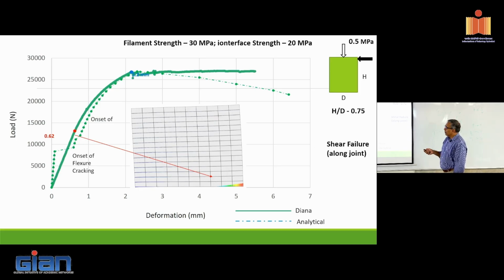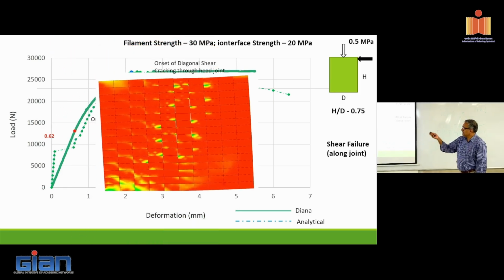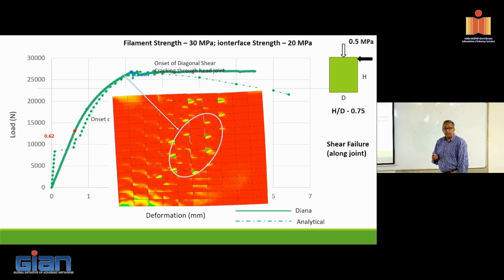Now I can do a micro model. Micro models are available where the constitutive models of these horizontal and vertical lines represent the mortar interfaces. And I can get the constitutive properties from the shear tests under confinement. Once I get that, I can calibrate the constitutive model and I can start doing predictions of things like this. This is for a masonry panel, right?